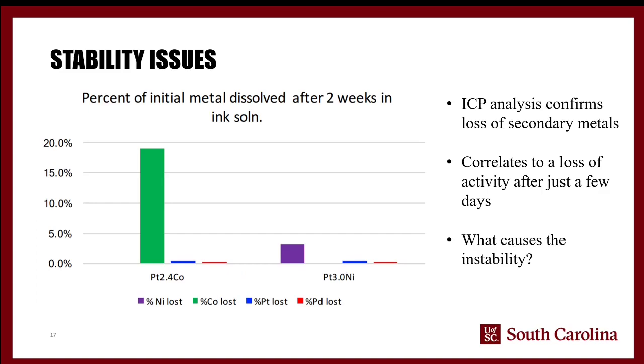But with all good things, there must be some bad. And in this case, what we found was that there were some pretty significant stability issues. The way this actually manifested initially was, with the platinum 2 cobalt and the platinum 3 nickel, I had gone back to repeat them a third and maybe even 4th time just to make absolutely sure that the activity was true. But I used an ink that was about 2 weeks old.